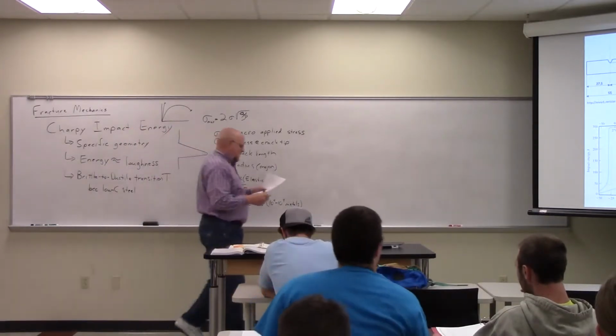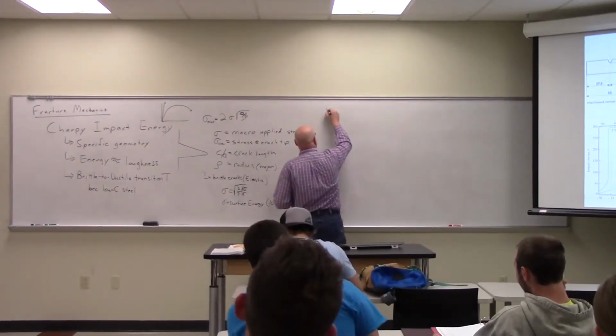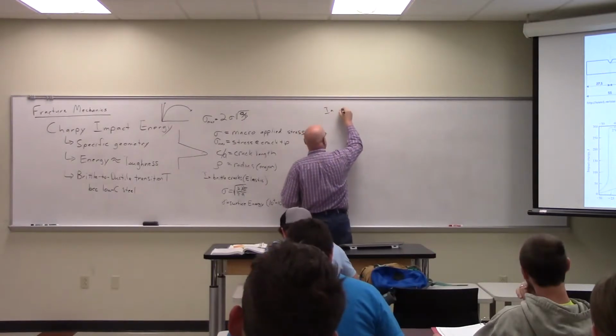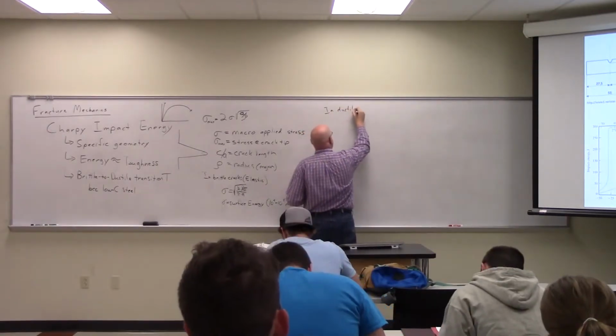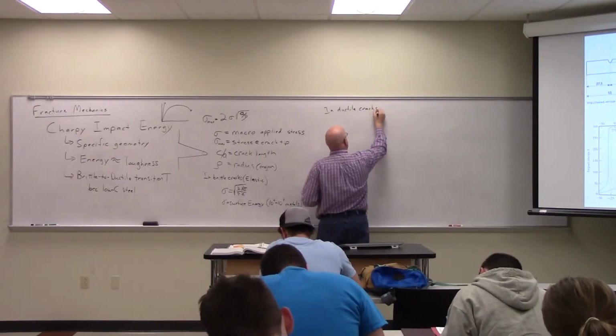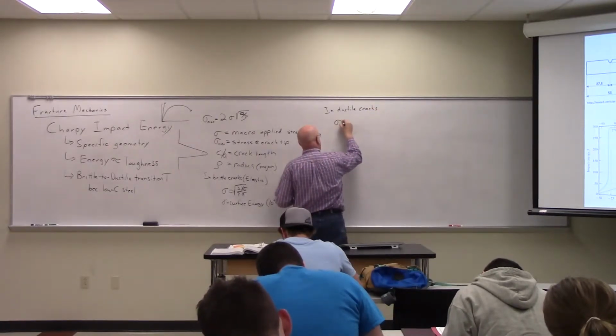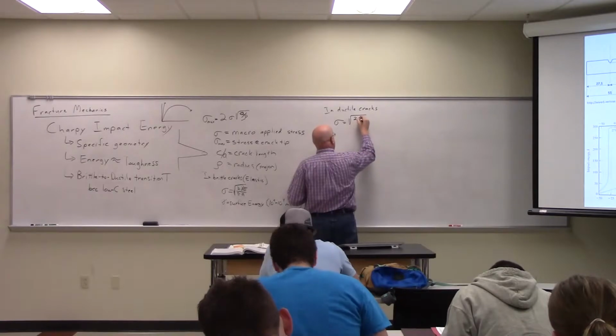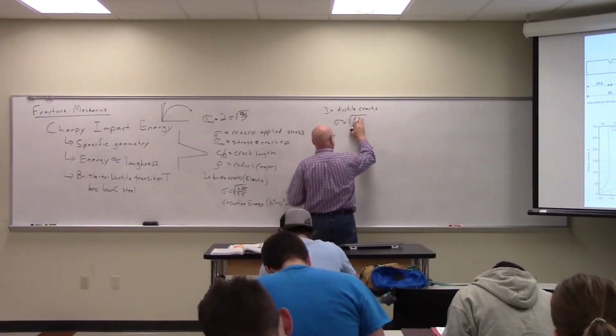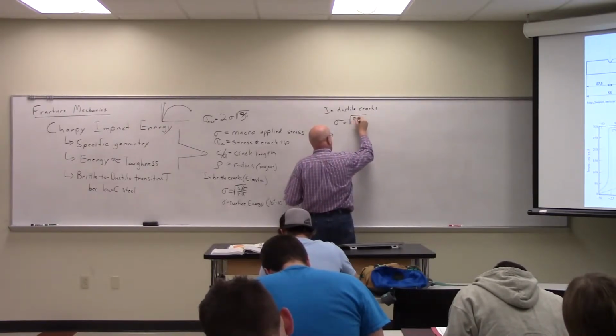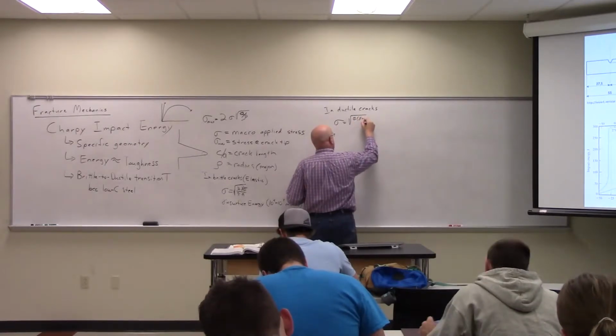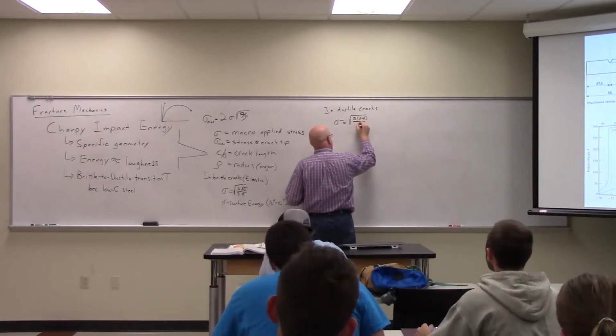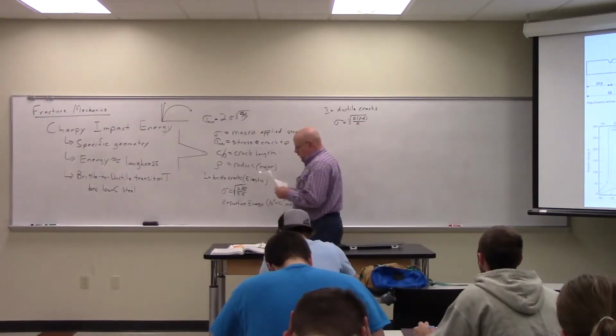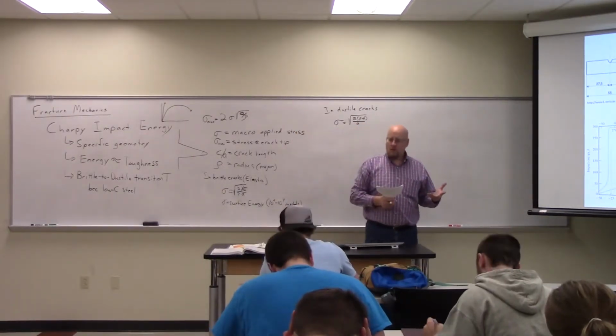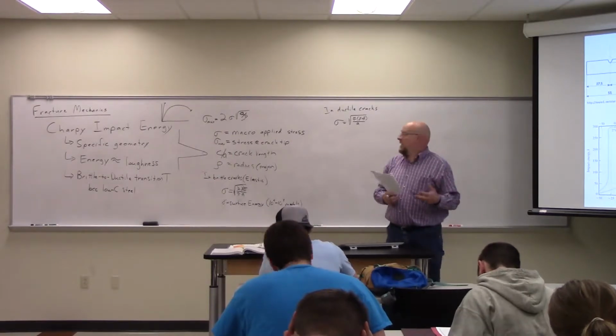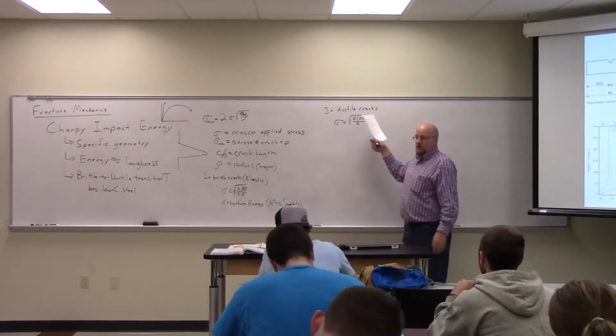For a plastic crack, for a ductile crack, in ductile cracks, we have a similar kind of relationship. Square root of, I'm sorry, not 2. E times gamma plus P over A, where P now is the plastic strain energy. It's not the elastic modulus. E is the elastic modulus, P is the plastic strain energy.